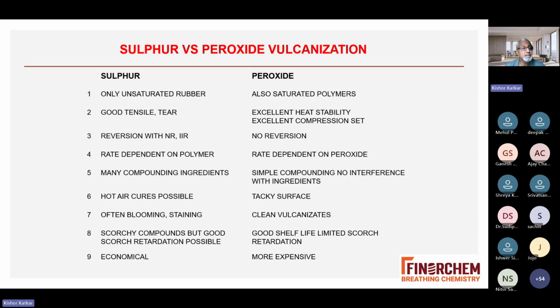Hot air cure is possible in case of sulfur. In case of peroxide, you get a tacky surface. Why? Because in hot air cure, air reacts with the peroxide, and the peroxide will not be available for cross-linking. So peroxide will get consumed by the air reaction, and the surface will be tacky. Often blooming in case of staining, that we have seen: in case of sulfur, if you are using normal sulfur, it will bloom out in the unvulcanized compound.